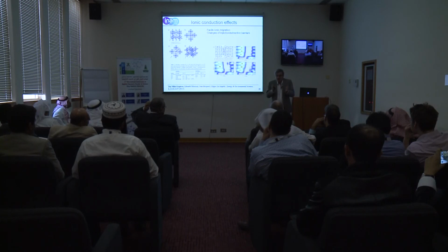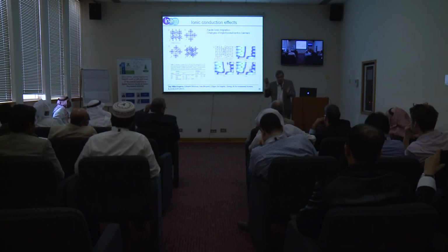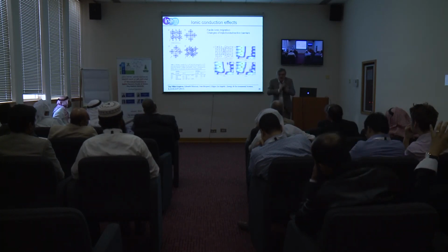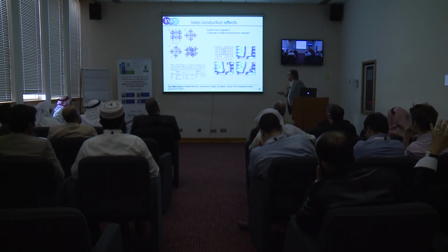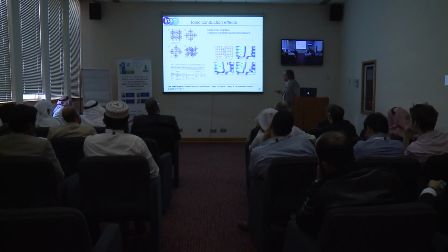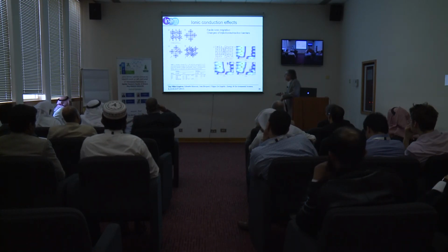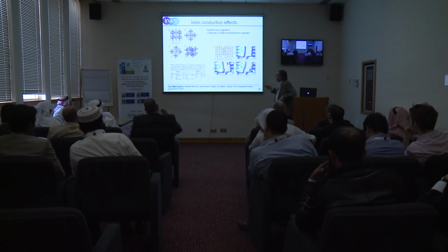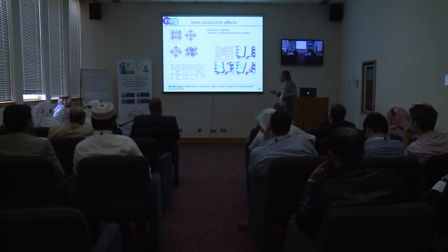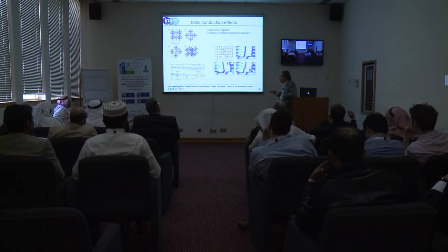They do give current at some frequency, but when you go at low frequency, they can give only capacitance because they accumulate on the interface and cannot go further. Okay. So this is a study made by the team of Filippo De Angelis, and I was giving some idea also about hopping of the ion migration, going from one interstitial to the other, and calculation of activation energy. And this is the iodide vacancy, we cannot see very well, which has very small activation energy, like 0.1 electron volt, so this is very likely.